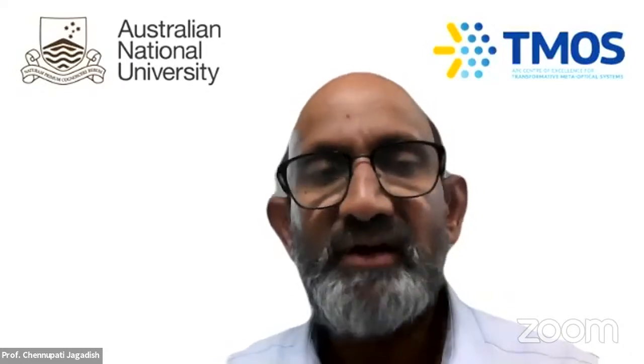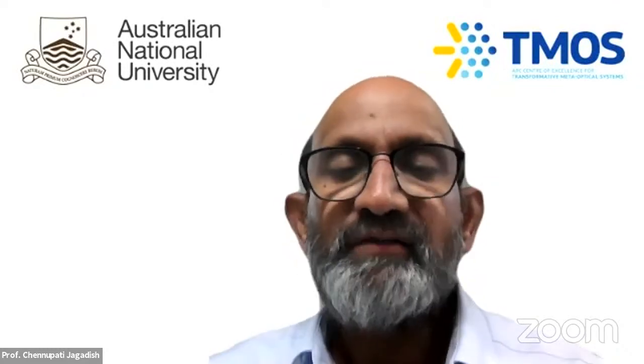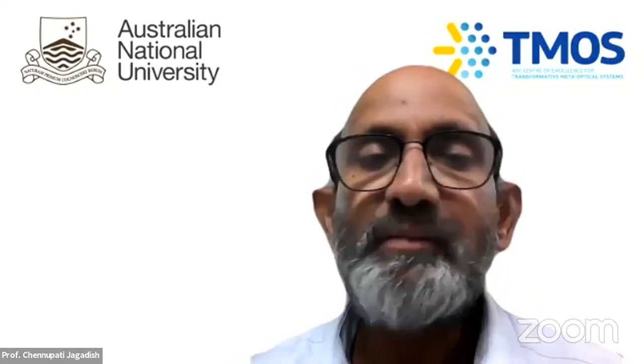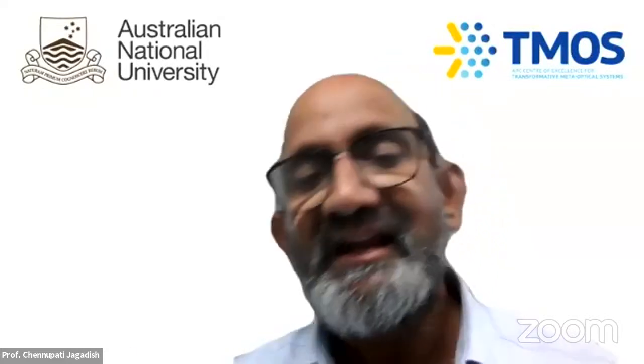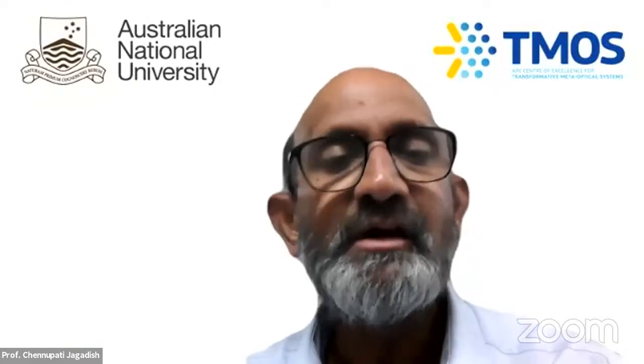And then mostly what we do in our laboratory is time-resolved photoluminescence, and that helps us to do the lifetime measurements. The smallest ones we can measure are up to 50 or 60 picoseconds or so. But whenever we want to measure picosecond lifetimes, we go to Oxford University, where they do the so-called optically pumped terahertz conductivity measurements, and it also gives you the lifetime of the carriers and other things as well. And also we work with our colleagues at University of Cincinnati. Again, they do time-resolved photoluminescence measurements. And these are all done in single nanowires, not ensembles, which is challenging, and that really makes it exciting to precisely quantify these things.